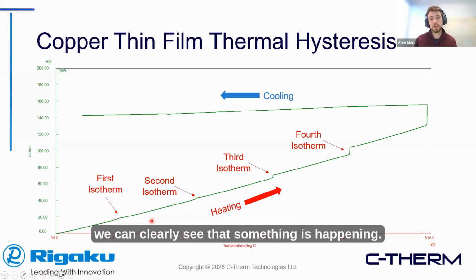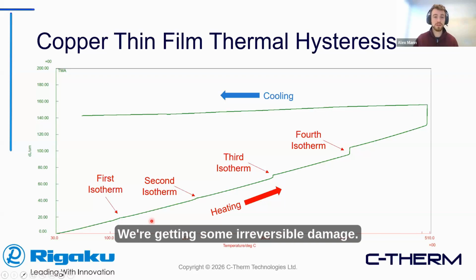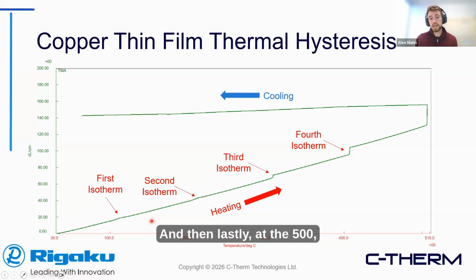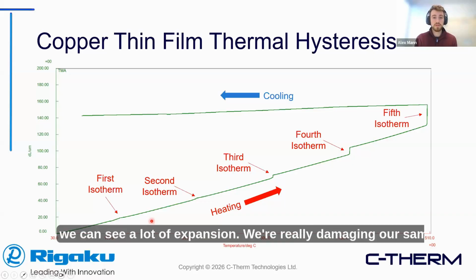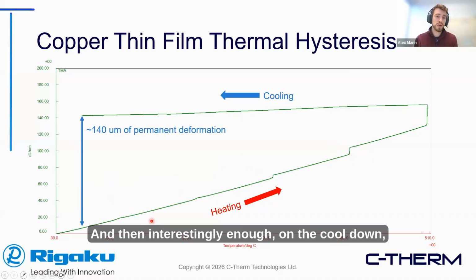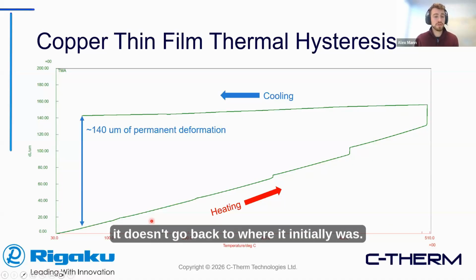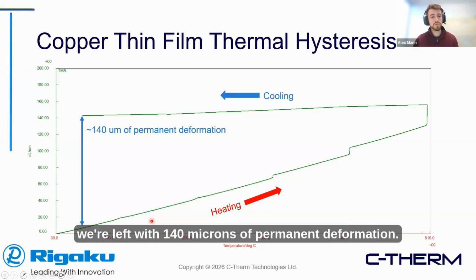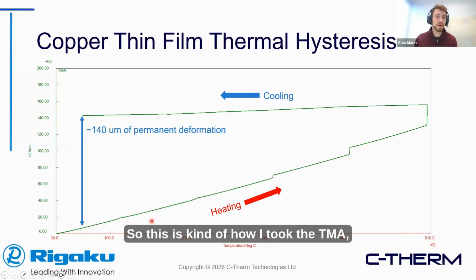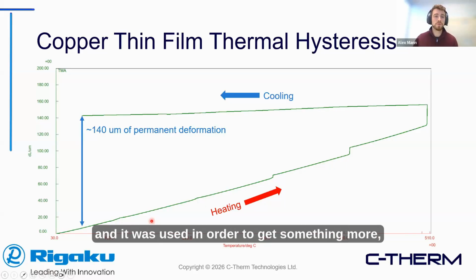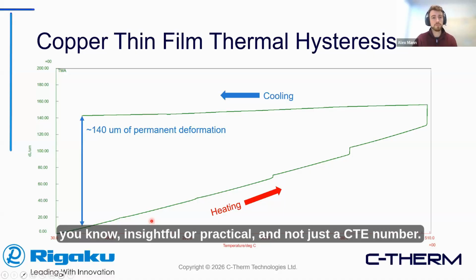The fourth one, we can clearly see that something is happening. We're getting some irreversible damage. And then lastly, at the 500, we can see a lot of expansion. We're really damaging our sample. And then interestingly enough, on the cool down, it doesn't go back to where it initially was. Because it's been damaged, we're left with 140 microns of permanent deformation. So this is kind of how I took the TMA, and it was used in order to get something more insightful or practical, and not just a CTE number.